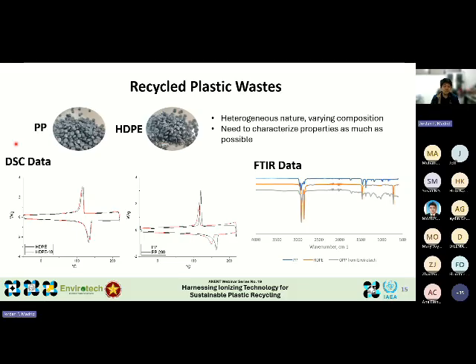We then performed characterization studies to evaluate the material properties. In this slide, I show some of the data, particularly from the differential scanning calorimetry test and the Fourier transform infrared spectroscopy test. In the DSC data, the results are consistent with the known properties of the plastics. For example, the recycled HDPE showed a melting point around 130 to 140 degrees Celsius, while the polypropylene, the black one, melted at about 160 to 170 degrees Celsius. That conforms to many published values for their melting points.